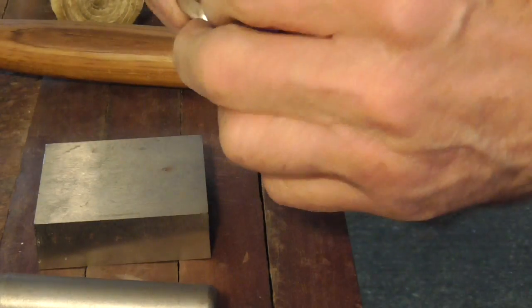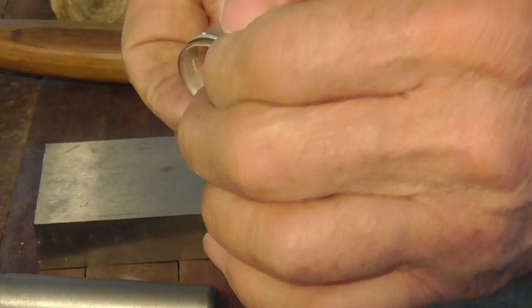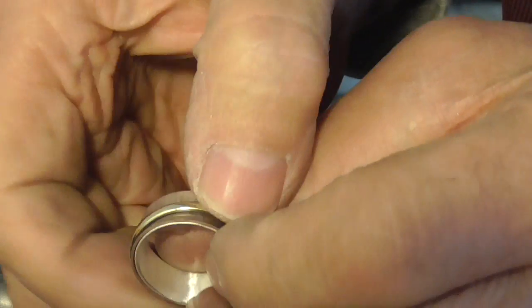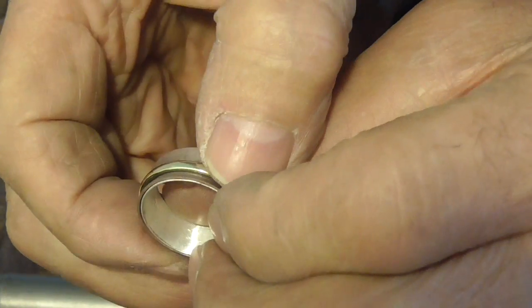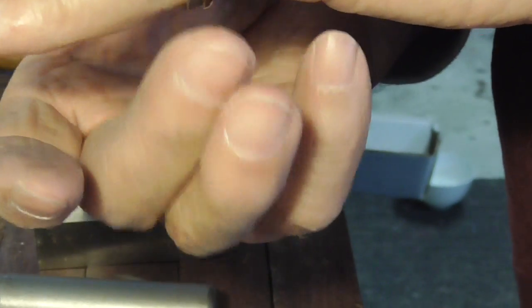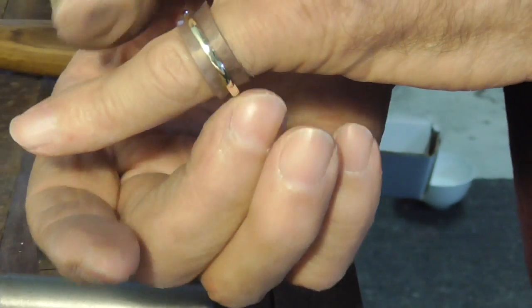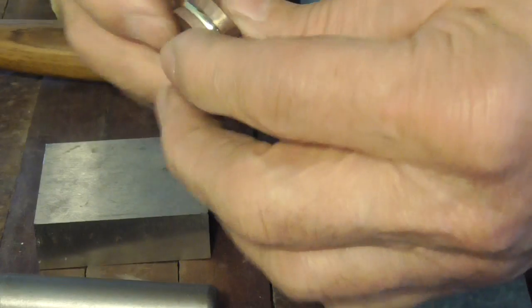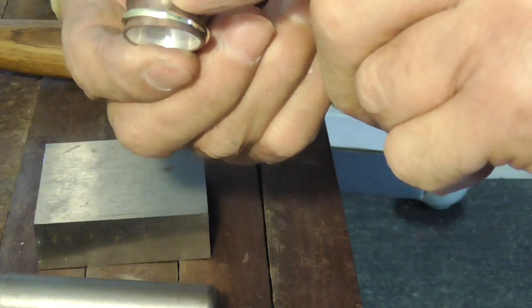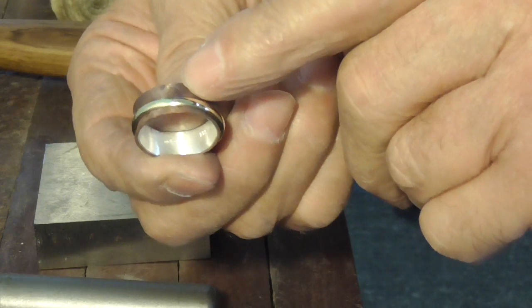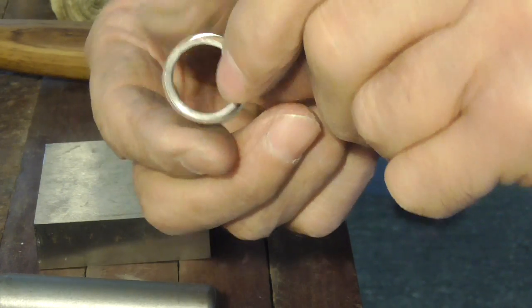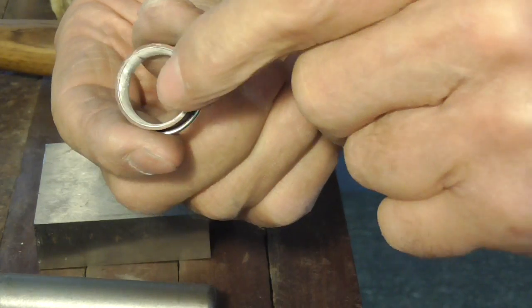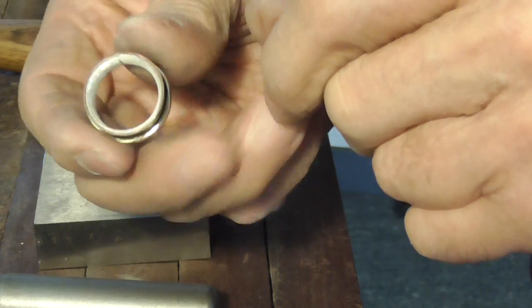And we don't want to flare it enough that the outer ring doesn't move. So this one still moves quite nicely. And that's it. The ring is done. Fits perfectly. This moves enough to annoy your neighbor. And we have, for this one, a dark outside, the brass, and a polished satin silver finish on the inside.